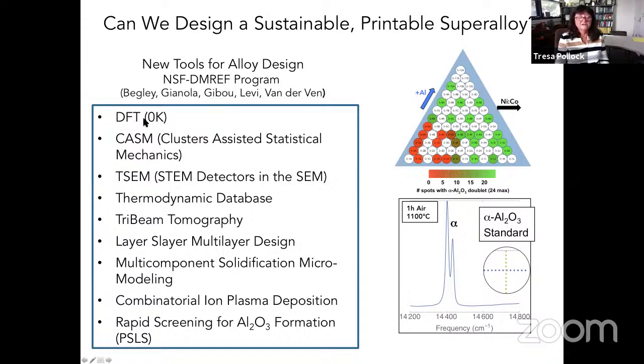And among these tools are density functional theory, coupled with Anton van der Ven's CASM infrastructure, which basically allows you to do the finite temperature aspects of alloy design. In situ experiments in the SEM, where we can watch dislocation glide and connect that to the fault energies that we calculate by these techniques, thermodynamic databases, our tri-beam system, calculations about coatings, because one usually needs coatings, the solidification aspects, and then finally the oxidation part of the story, which in brief is really a difficult problem because oxides are hard to be predictive about in terms of compositions and use of DFT.